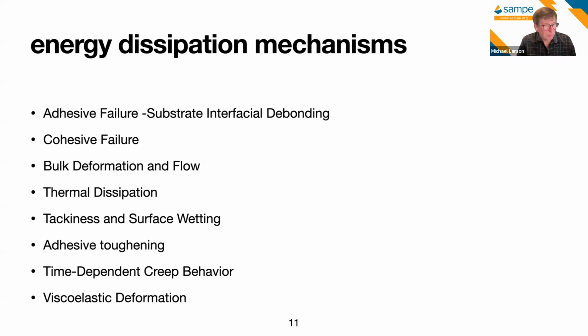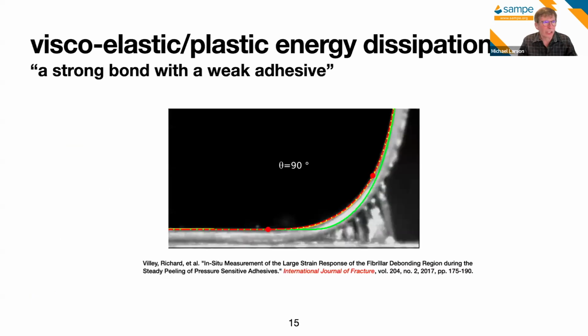We find people are beginning to add things into the adhesive in order to give some kind of analogy to the fracture world, an R curve kind of behavior, something that Dr. Chen did a lot of work with in the past. There's time-dependent creep behavior. So there's viscoelastic and viscoplastic things going on in this. And it's this last one, the viscoelastic deformation, that really is the twist that can work for us a lot. And if we don't account for it properly, we'll miss the boat in choosing the right adhesive.